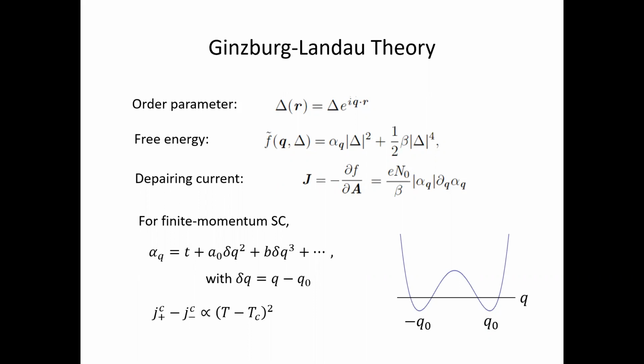And if you are in this finite momentum superconducting state, then we should look at the behavior of the quadratic coefficient in the vicinity of the minimum Q naught. And in this case, you see that in general, there's an asymmetry between the forward direction and the backward direction. This is captured by including a simple cubic term in this expression for the quadratic coefficient. And this then leads to the fact that the critical current in the forward and backward direction is different. And the difference is proportional to the reduced temperature squared.